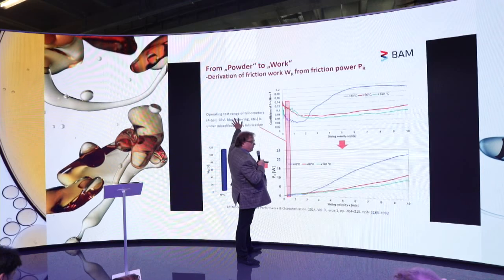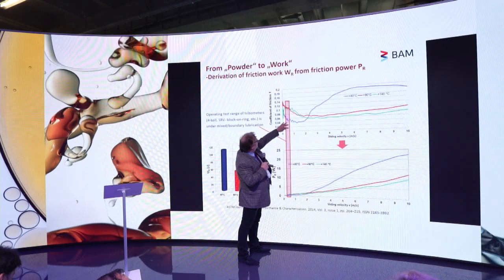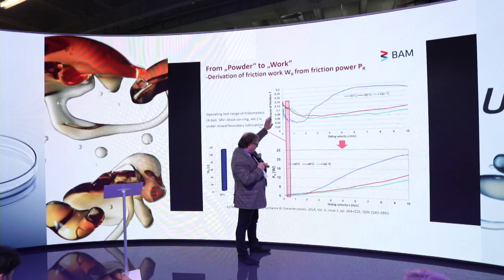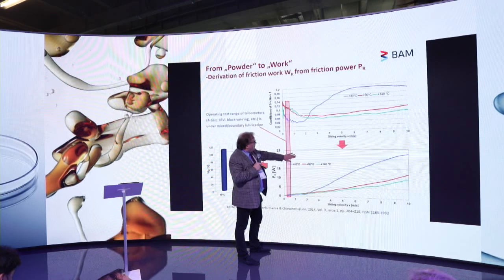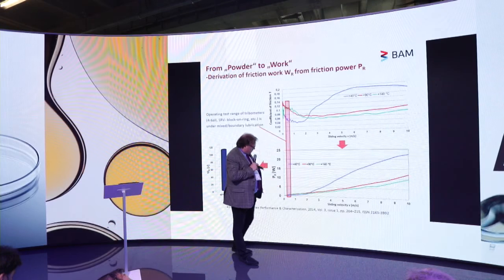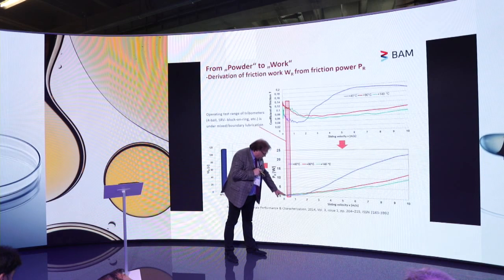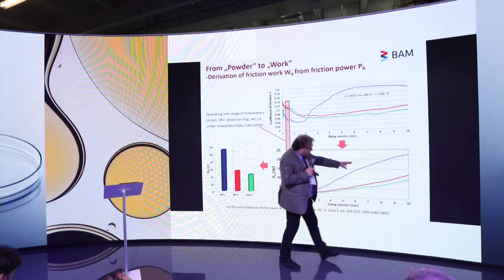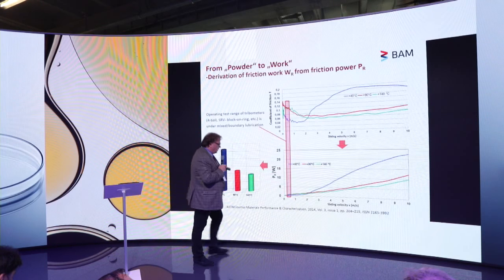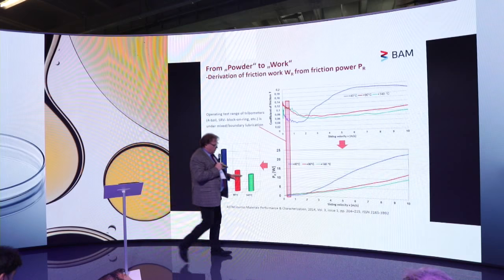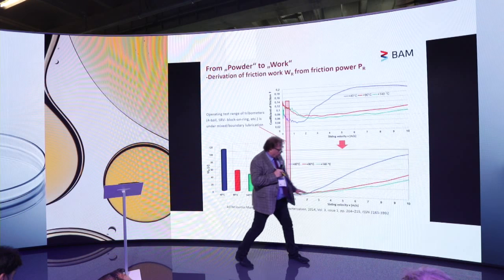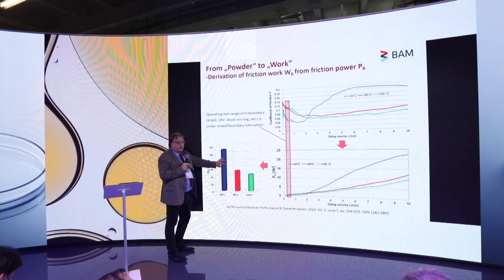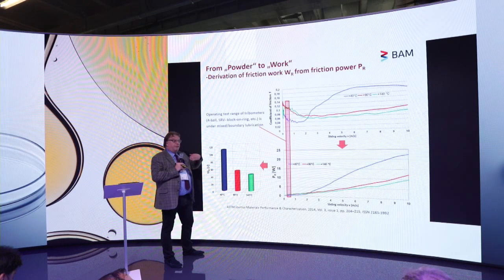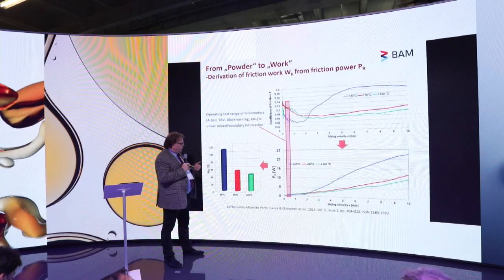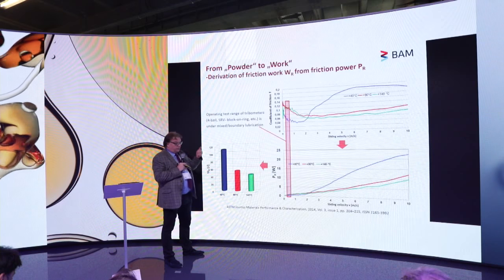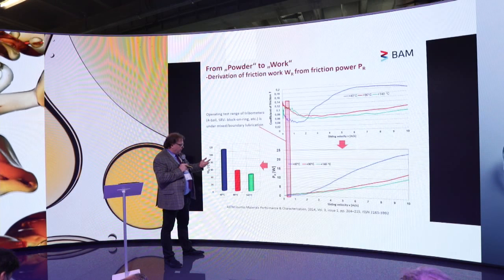But as said, the test equipment only works here. When you convert the friction into power, you see that the same curve changes. This is a problem of this test equipment. We measure here, but here is a big friction as power, and this now you convert into work. You take the whole surface below, and then you have a new figure to rank engine oils, but you now have the whole Stribeck curve. It means dry friction, mixed and boundary, and hydrodynamic.